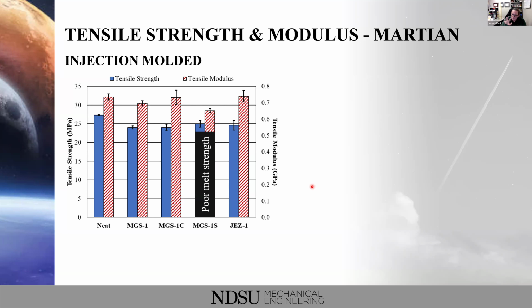But just through observations, one thing that we noticed was the sulfate. This MGS1S is the regolith that has a little bit more sulfate in it than the rest of them. It had really poor melt strength, to the point that it was nearly impossible to pull strands and create our pellets in extrusion. And in injection molding, it just drooled out the nozzle at the end of our injection molder. It was very difficult to work with.